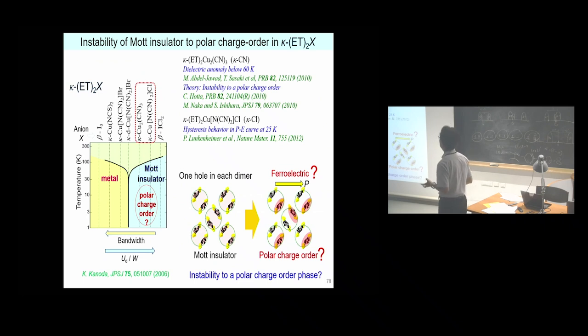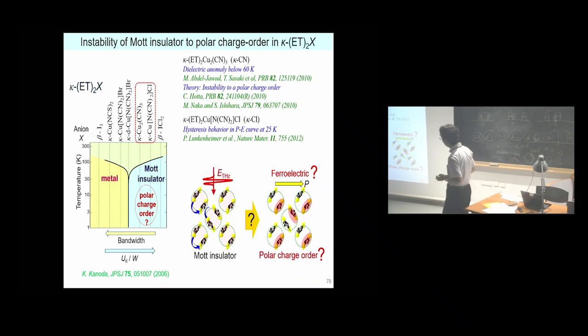Okay, let's go back to the kappa-ET2X compound. The previous theoretical studies and dielectric measurements suggested that these two Mott insulator compounds, far from the metal-Mott insulator boundary, include an instability to a polar charge order phase, in which the charge of a hole is disproportionated in each dimer in a specific direction, like this. If such an instability exists, the terahertz electric field may induce a transition from Mott insulator to polar charge order.